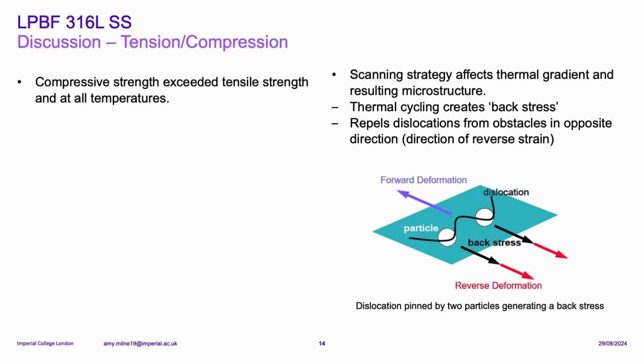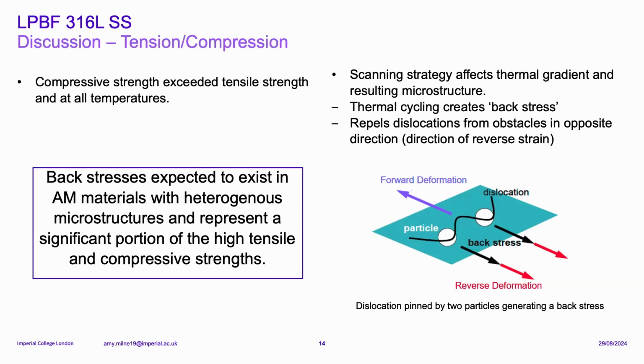Because the scanning strategy affects the thermal gradient and creates a back stress, which resists the forward motion of dislocations but allows them to slide back inside grains. So you've got an element of kinematic hardening present, which is accounting for the difference between tensile and compressive strengths. So the back stresses exist in these materials with this microstructure, and they represent a significant portion of the high tensile and compressive strengths. This agrees with some other work which found that the back stress was equal to the difference between the wrought yield strength and AM yield strength.